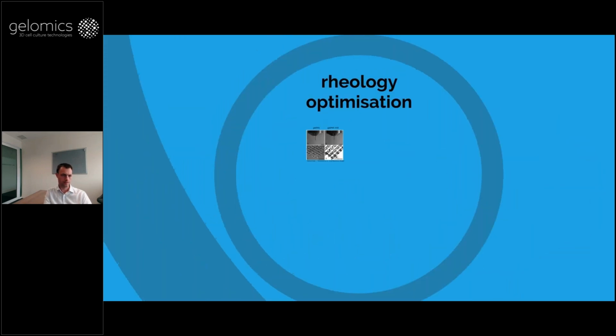So with optimizing rheology, you can add different components. Our first try was hyaluronic acid, which increases the viscosity a lot. So that helped to get it from dripping from a needle to actually making a filament. It's more viscous, it still keeps flowing. So you still need to be pretty quick with photocuring to not lose the fidelity of the structure you've printed.